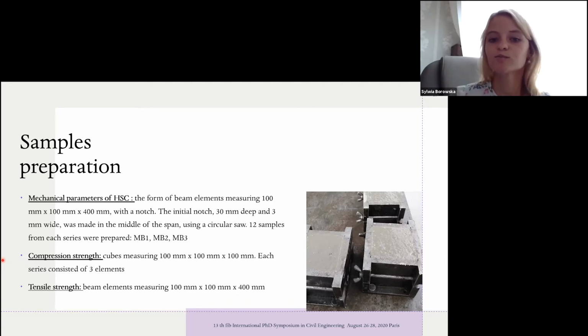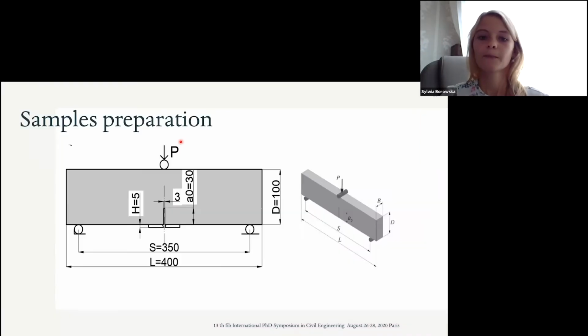the mix and to prevent the formation of empty space associated with worse workability. The fibers were added to the concrete mix in stages, alternating with a mixture of water and superplasticizers, to prevent the formation of hybrid fiber clusters. These figures illustrate the geometry of samples for specifying the fracture mechanics parameters and the load scheme of the test.